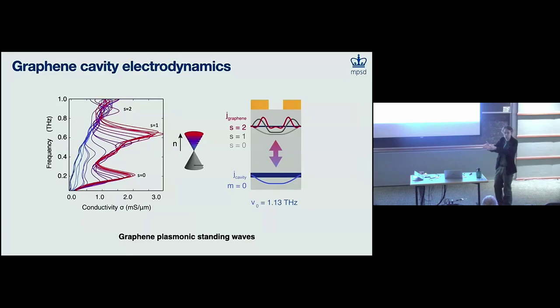So that is a tuning parameter we have, but we can go between 1/3 microns to 1/10 microns. But you measure the group velocity reduction directly. Yeah, in general, we measure group velocity reduction, and that we can see. But in terms of k, your other question was about momentum dependence. That is not something we can easily do. We have to build a new device every time, and because these devices are all 5 to 10 microns, there's only so much we can do.